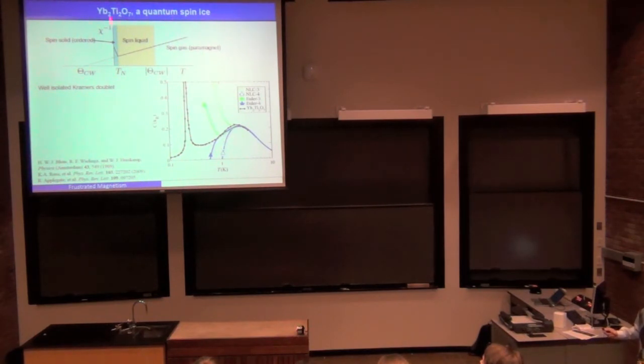If we look at the inverse susceptibility, then at high temperature in the paramagnetic, it follows the Curie-Weiss law, and by looking at behavior at high temperature, you can define a Curie-Weiss temperature. And then as you go down in temperature, most material will eventually order, so there is a Néel temperature. And below this temperature, people call it spin solid because there is long-range order. But an interesting thing happens between the Néel temperature and this Curie-Weiss temperature, which usually tells you how strong the spins are interacting. And here is usually where the spin-liquid physics would apply.